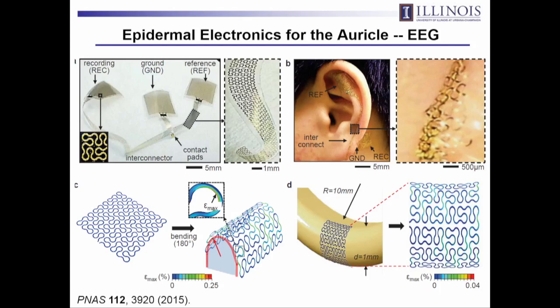And then I can change the configuration of that Peano fractal for the interconnect wiring to provide stretchability along the length, but not that much along the width. So you put it together, in this case, designed to not only stretch, but also conform to the complex topology of the auricle. And here we have a recording electrode on the mastoid for measuring brain waves. And we have reference and ground electrodes on the ear.